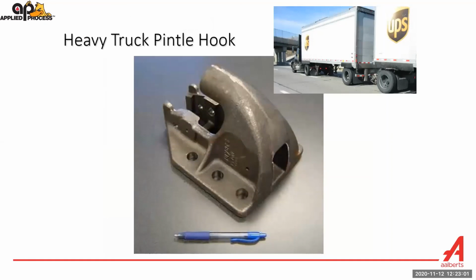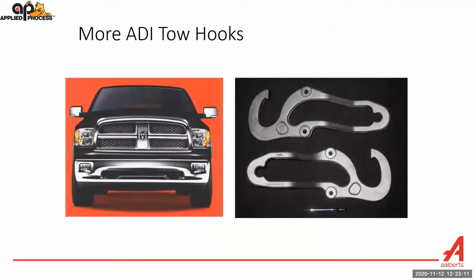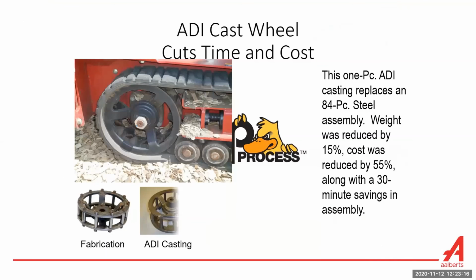If you're driving down the road and you see a tandem trailer truck, the pintle hitch in between is usually made out of Aust-tempered ductile iron. Tow hooks on light vehicles have been made out of Aust-tempered ductile iron. And this is an 84-piece fabrication assembly that was converted into a 1-piece casting. Weight was reduced by 15%, cost was reduced by 55%.